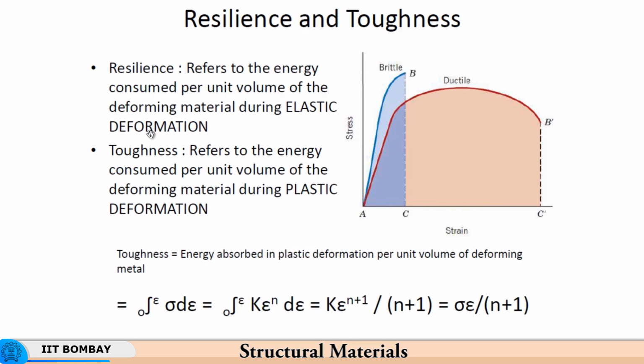So, we distinguish now between the energies. I told you about the energy which is stored in a material under elastic conditions and it is useful for making springs. So, this is called as resilience. So, elastic energy stored in the material due to the elastic deflection is the resilience, whereas toughness refers to the energy consumed per unit volume of plastic deformation. So, you have integral sigma d epsilon from 0 to epsilon. In case of elastic energy this will be up to the strain corresponding to the yield point, and so you will have d epsilon will be equal to sigma by E, that is Young's modulus, and so you will get the corresponding equation over here.